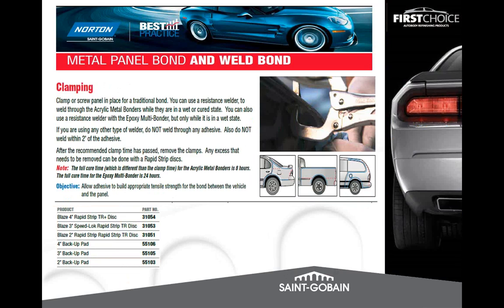After the recommended clamping time has passed, you can remove the clamps. You can remove any of the excess glue with a rapid strip disc, or if it's not fully cured, you can clean it off with the panel adhesive cleaner. And there's a note here that full cure time is different than clamp time. For example, another advantage of an acrylic is no matter the temperature, it's going to take 8 hours to cure, where a 90-minute epoxy is 24 hours.